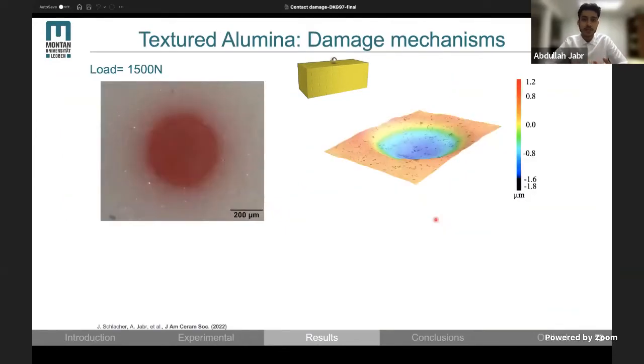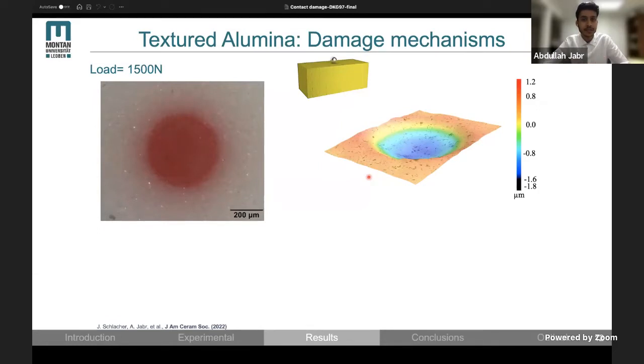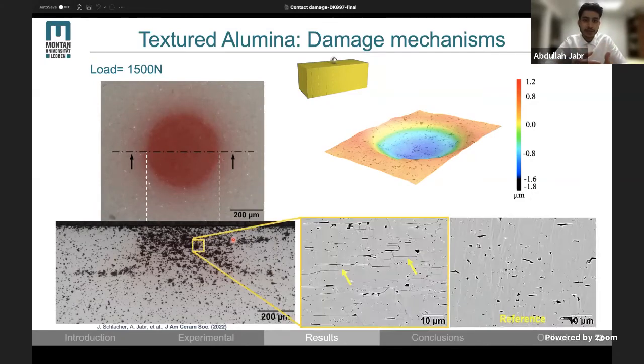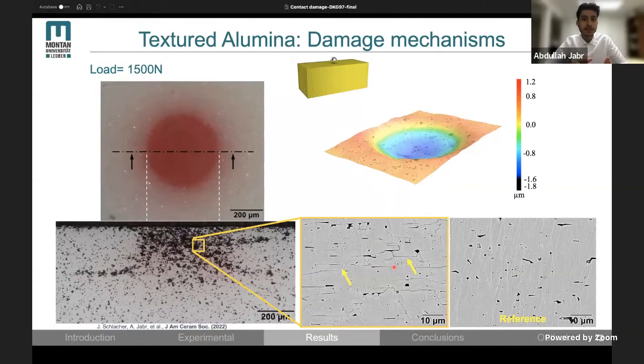Let's take a closer look at the damage mechanisms. Here you can see the surface of a sample loaded at 1500 Newton. Looking at the 3D confocal image, we can clearly see the surface depression, which is very interesting as it looks similar to indentation damage that we know from ductile materials such as metals. This means texturing gives us some sort of quasi-plasticity. Looking at the subsurface, we see again some traces of damage. Because of the act of grinding and polishing, we only see some grain pull-outs. In order to see what is exactly happening, we used the ion slicing technique. As you can see, there are multiple cracks oriented horizontally along the grain boundaries of textured grains, indicating that the damage occurred in response to shear stresses by some sort of an interfacial shear sliding mechanism.